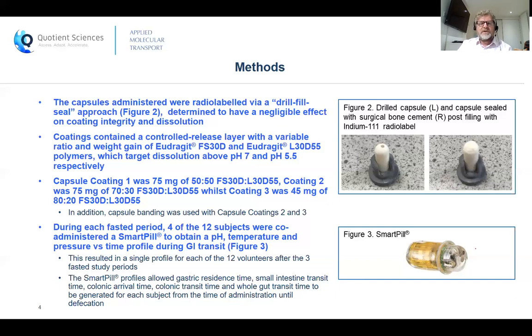As mentioned earlier, we also took the opportunity to generate a single reference pH, temperature, and pressure versus time profile for each volunteer subject in the study by co-administering a smart pill in a different set of 4 subjects during each of the 3 initial fasted periods of dosing. And this allowed us to compare transit times from the smart pill against the radio-labeled coated capsules on at least one occasion for each subject.